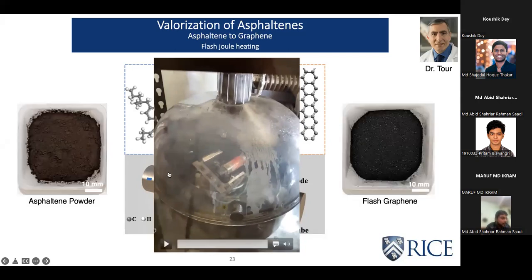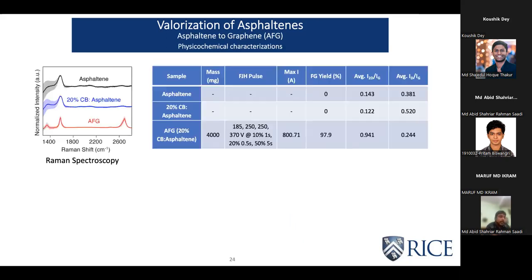Basically, we give this asphaltene powder as the input, and at the end of the process we get this kind of material, for which, in other substances, the Tour group has found graphenic signals from the output material. So for our case, whatever we got from asphaltene, we had to check whether we have really formed graphene or not. And for that, we did Raman spectroscopy. Raman is a very good, widely used tool for confirming this type of graphene formation.